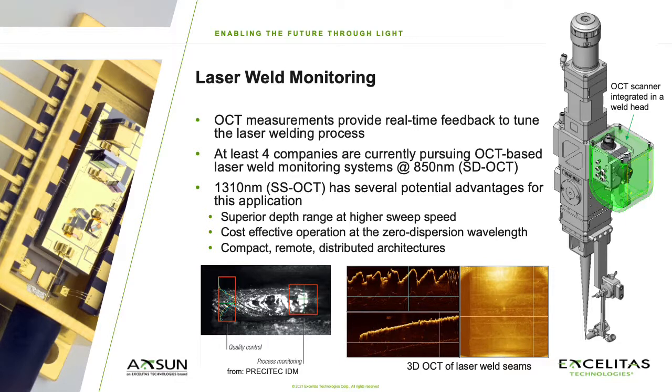Monitoring of the laser weld process by OCT can generate a variety of metrics that predict the quality of the weld, such as the seam profile ahead of and behind the weld, as well as the penetration depth of the keyhole during the weld. This is achieved by attaching the OCT scanning apparatus to the weld head camera port and introducing the image beam using a dichroic mirror. Measurements are available immediately, enabling welding process parameters to be tuned in real time. This is an active area of research and product development, with at least four companies exploring OCT-based imaging solutions for inline laser weld monitoring.